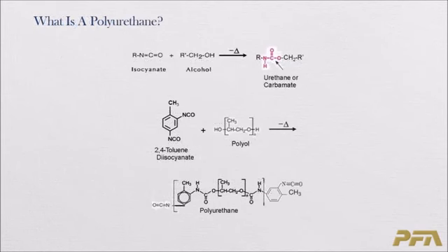So start out with, what is a polyurethane. By definition, a urethane is a chemical that has this structure here, NH, carbonyl oxygen. It's also called a carbamate structure. The most practical commercial route to forming that structure is by the reaction of an isocyanate with an alcohol.